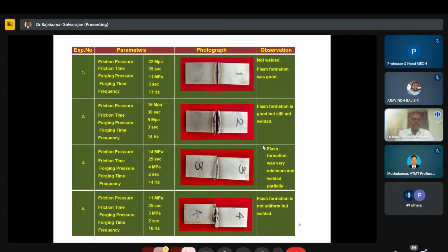Similarly, reducing the friction pressure, with friction time 30 seconds, forging pressure 5 megapascal, forging time 3 seconds, and the frequency increased to 14 hertz. Flash formation is good, but still not welded. Flash is formed, but the weld has not happened.